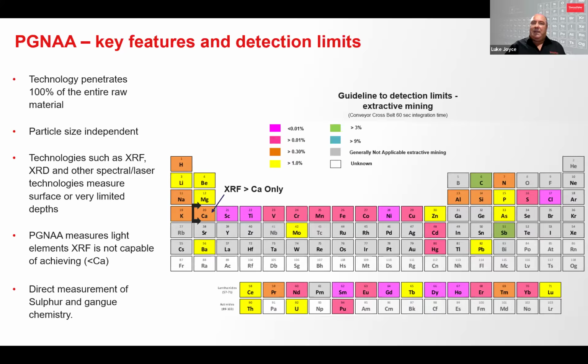Lab analyzers using these techniques require analysis under vacuum or in a helium-purged environment to measure light elements accurately, which is obviously not possible for online measurement. PGNAA, however, can accurately measure both heavy elements above calcium and lighter elements online, enabling real-time analysis of sulfur and light elements associated with gangue, which impact process control and metal recovery.